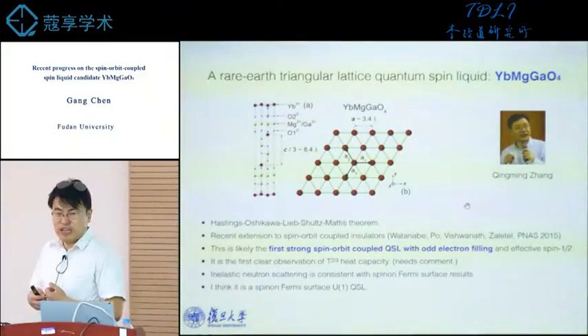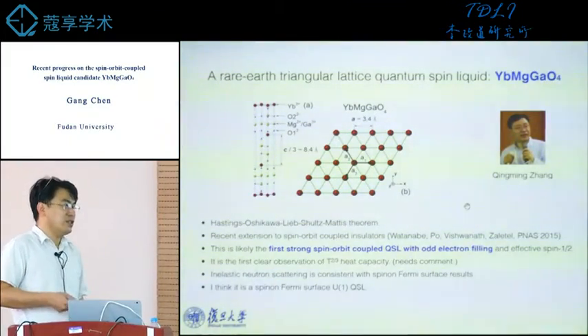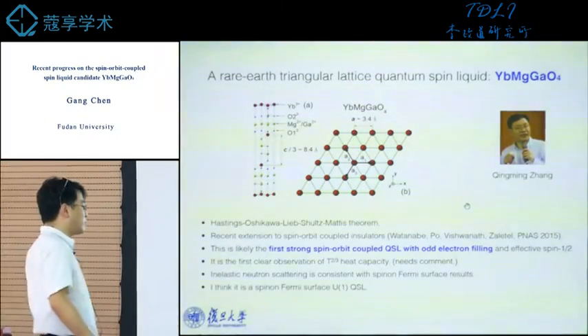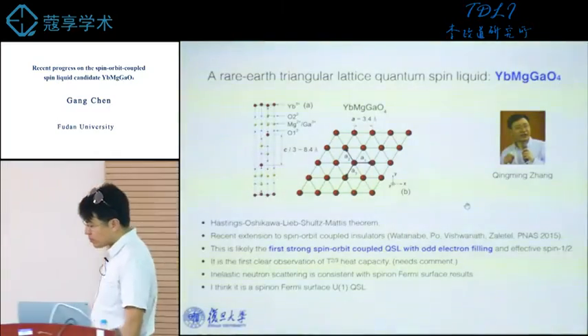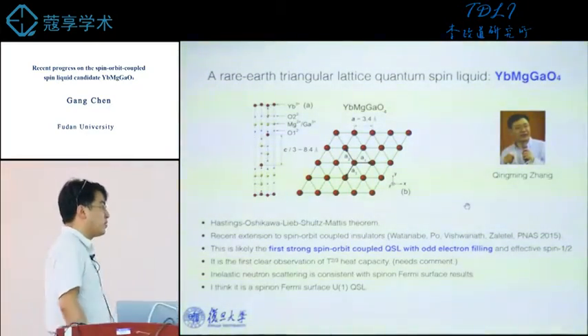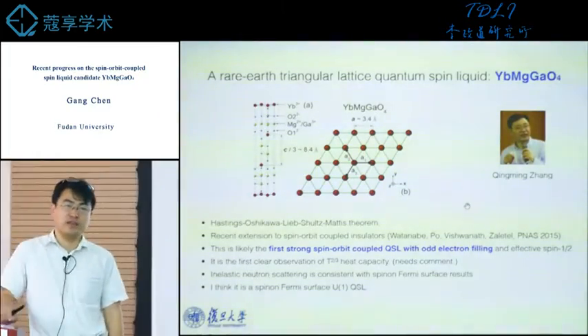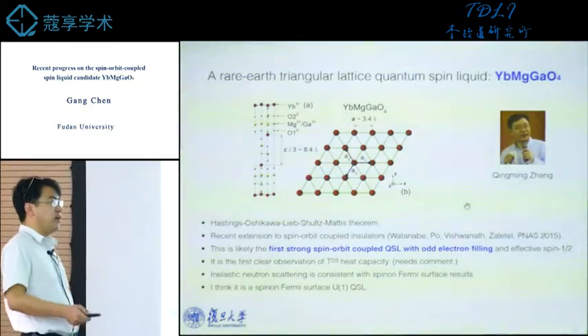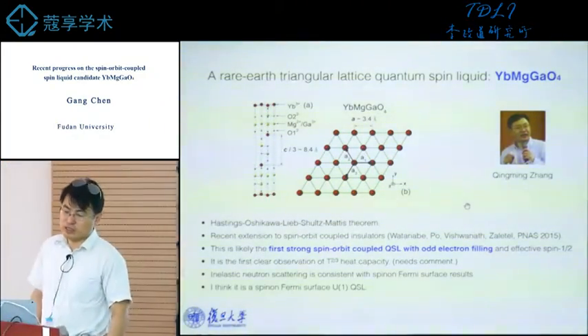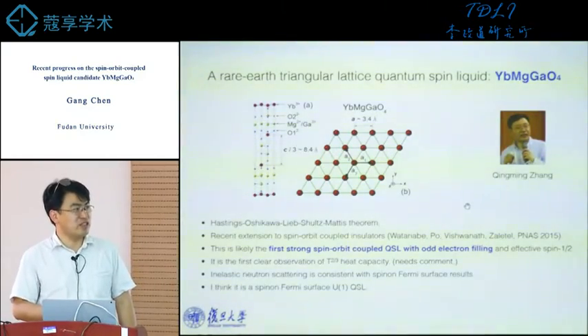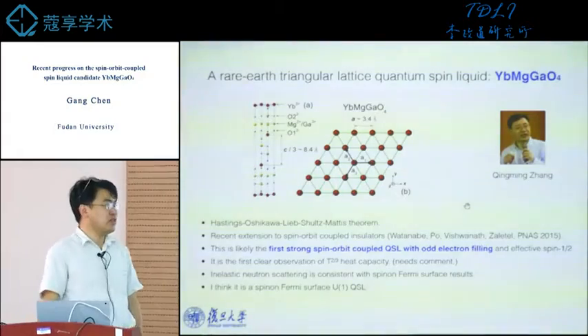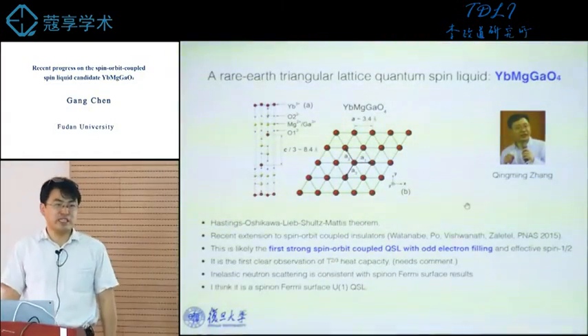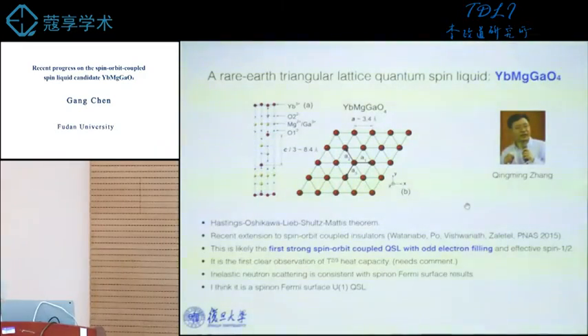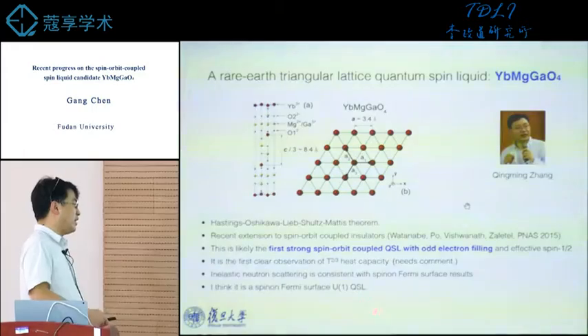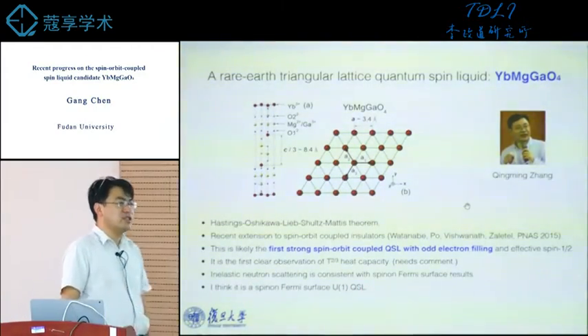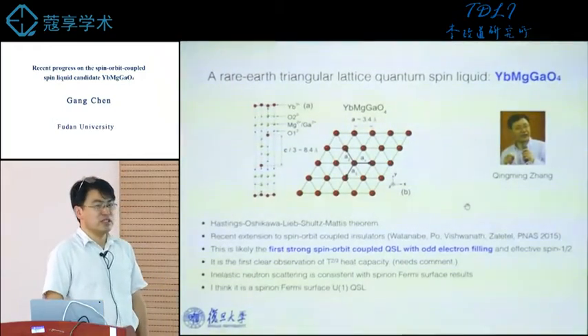But if you have gapless matter in the low energy theory, that will enhance the scaling dimension for these monopole events. So they will suppress these monopole events. The space-time monopole events will be suppressed by the presence of gapless matter. And it was argued that because a Fermi surface has a lot of low energy density of states, a lot of gapless matter, a U1 quantum spin liquid with a spinon Fermi surface can potentially be stabilized in that manner. That's the reason why this spinon Fermi surface U1 quantum spin liquid can potentially exist, due to the presence of infinite gapless points of the spinon matter.